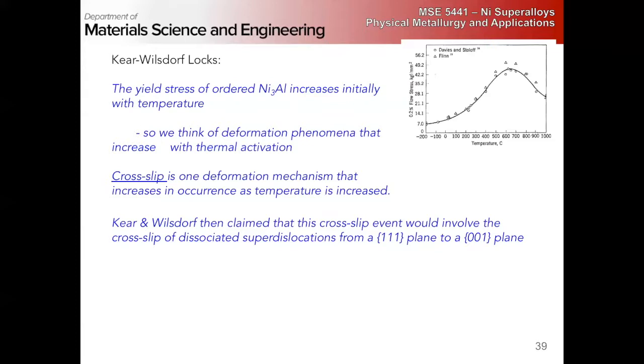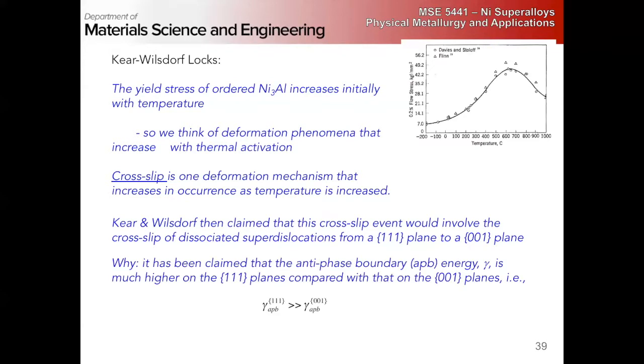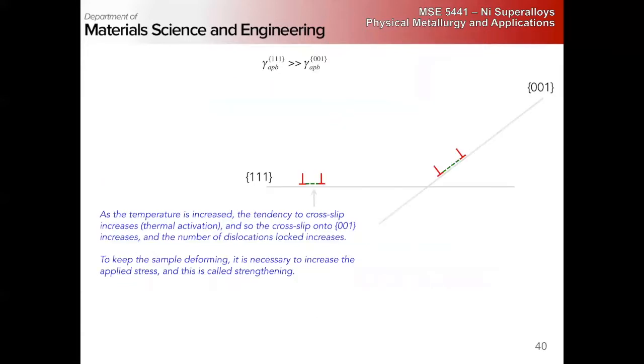Right? So why on earth would this happen? They made some estimates and said that the antiphase boundary energy is much higher on the 111 planes than on the 100 planes. So you've got these partials that are separated. They have an antiphase boundary. If they change planes, they can reduce that fault energy quite a bit, right? So basically, the picture looks like this. We have two partials on the 111. They both cross-slip onto the 001 plane, and now they're spaced farther apart because this boundary energy is lower. They can be farther apart and still reduce the energy, okay?